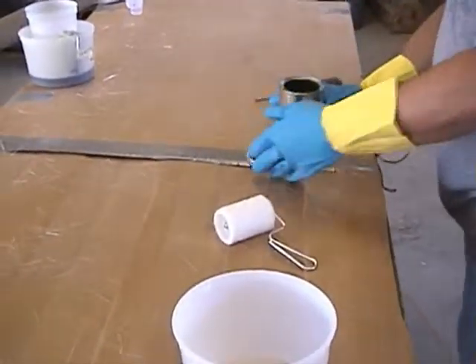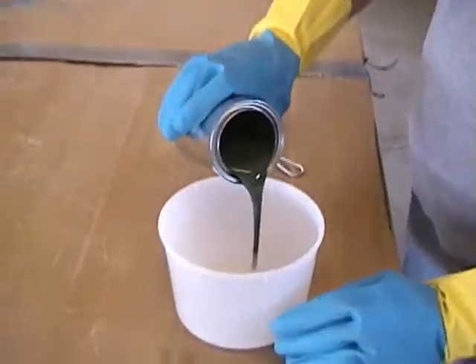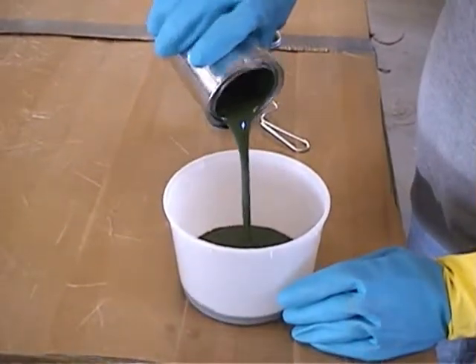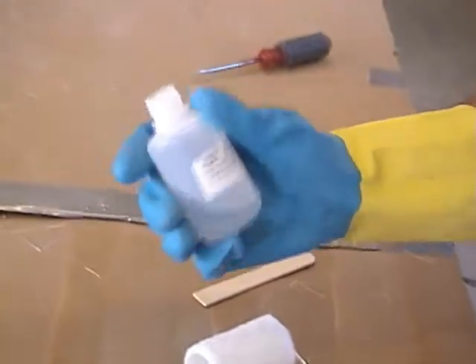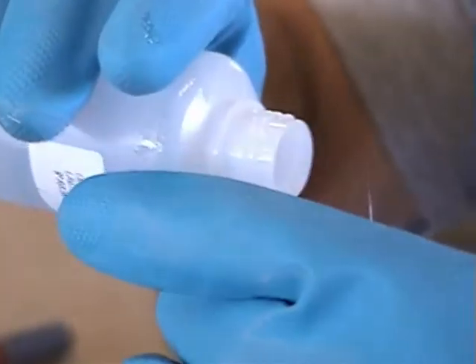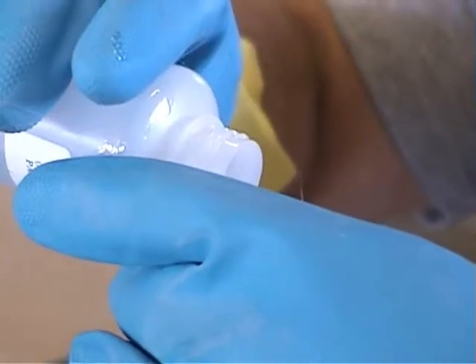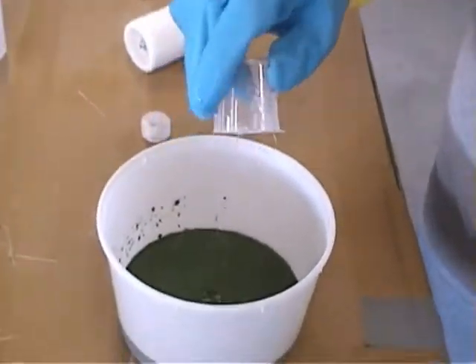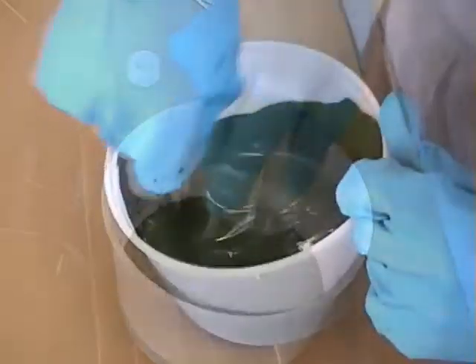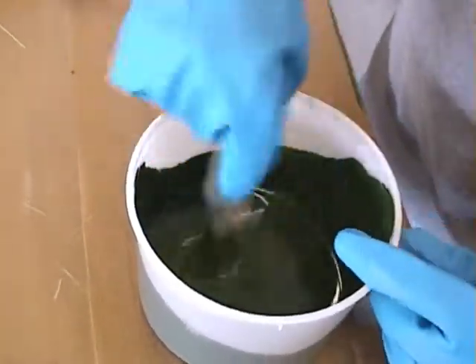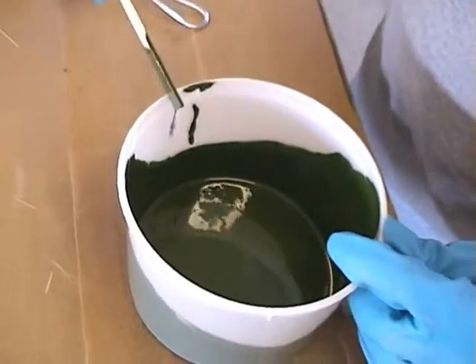The cover resin, which is a pigmented resin, will be the final layer you'll apply once the butt wrap has reached the B stage. You will use the same catalyst you used with the other resin earlier. Check your instruction sheets for the proper catalyzation ratio. Be sure to stir it very well until you see little bubbles as before. This indicates the resin is completely catalyzed.